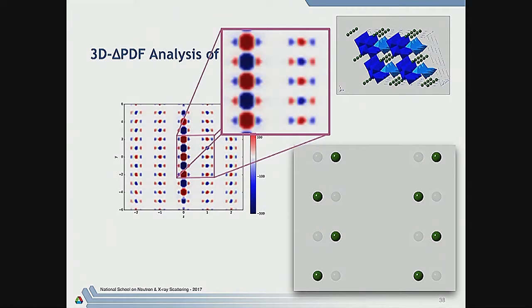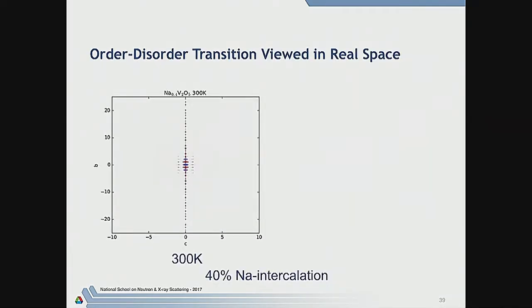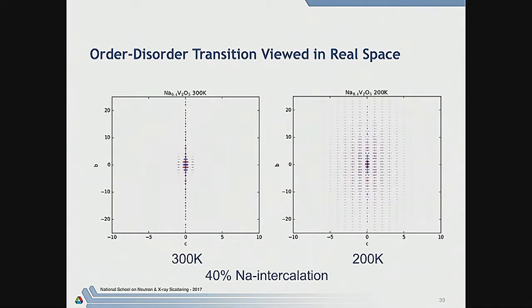configuration of sodium ions, which may not seem all that surprising given Coulomb repulsion, but you can also tell that they're in phase in neighboring rungs. Now, it turns out that you can actually also learn about the length dependence of this. So here we see at high temperature that we have rather small correlations between neighboring ladders. We go to lower temperature, we start seeing longer range correlations.